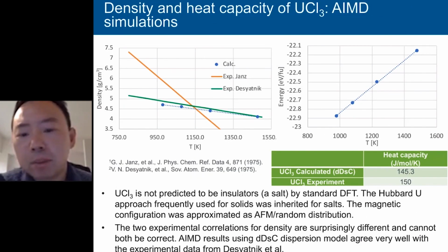So uranium chloride is much more complicated than the two salts I showed in the previous slide. David found that uranium chloride is not predicted to be an insulator at all by standard DFT. So the Hubbard U method has to be used to correct this. And the magnetic configuration was approximated by an anti-ferromagnetic model. Essentially, they're kind of random in the salt. With these very advanced techniques, David is able to calculate the density of the salt as a function of temperature. The results are shown as the blue dots on the left figure.